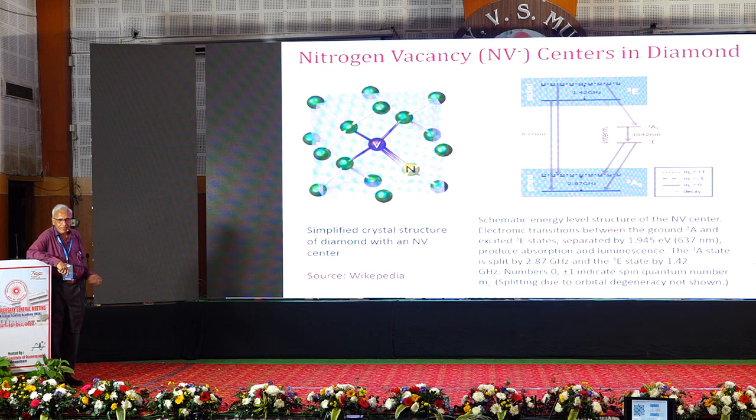So if you take diamond and replace one carbon with a nitrogen, it finds that energetically it's favorable to get rid of another carbon from a neighboring site if you try to heat it and then anneal it, and form this pair called nitrogen and then a vacancy, and it gets singly charged. So it's called the NV minus center.